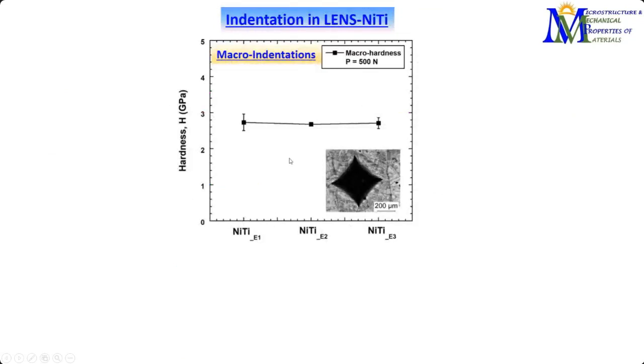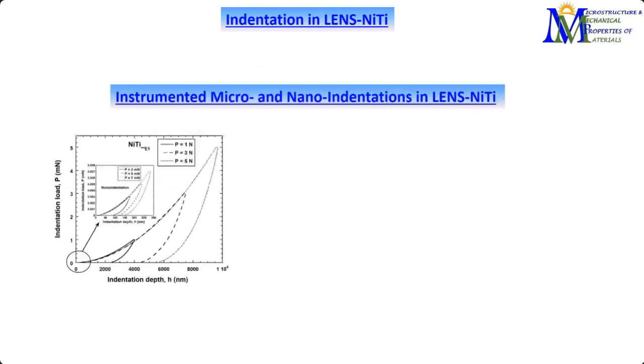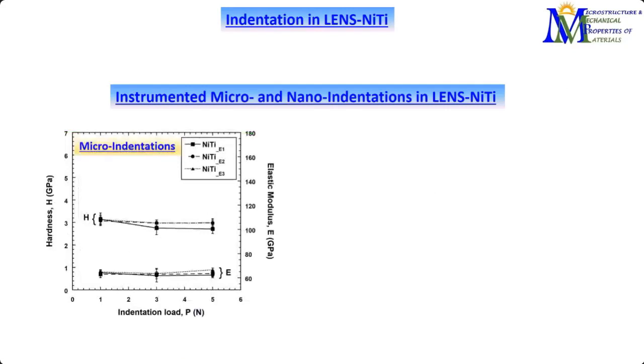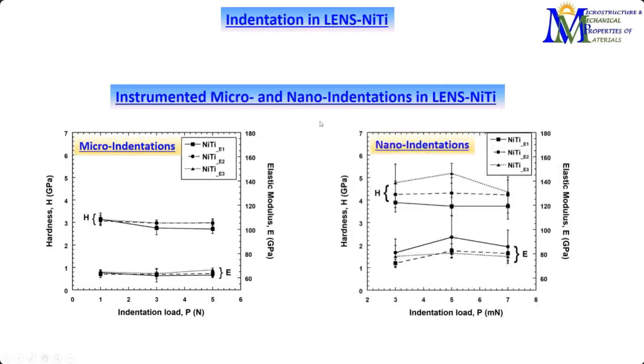The first thing we did was macro indentation with a very high load, 500 Newtons, and we could not see any difference in the hardness. We were very happy about that—although we changed the processing parameters significantly, there was no such effect on hardness behavior. But as we did the micro and nano indentation, things were different. Particularly in nano indentation, we saw a huge change in hardness, reflecting the change in the phases present and the local structures of the grains.